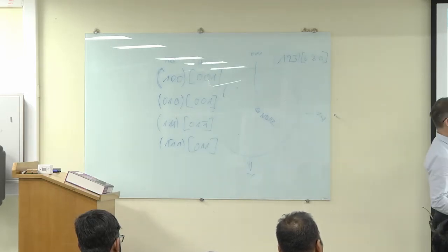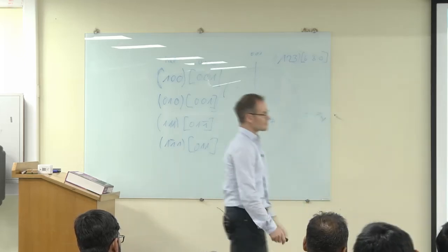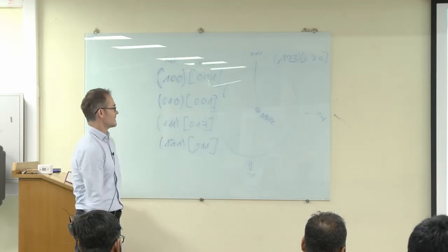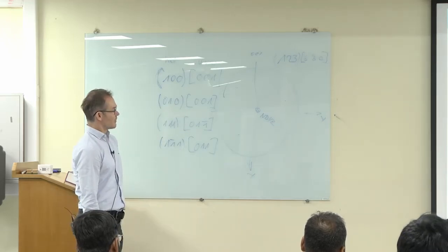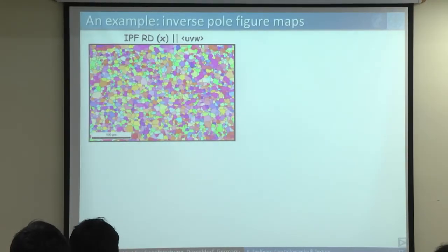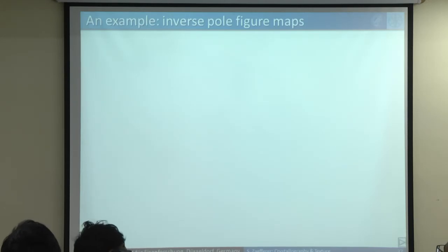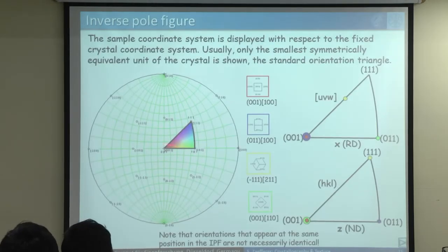And that means this crystal here, for example, if we would plot it now in the map, we would give it a red color. Yeah? Red for both, 001 is red and 100 is also red, and so on. And that's actually the inverse pole figure map, which we then see very frequently when we use EBSD. We are actually taking these colors out of the inverse pole figure, why is it not coming? Out of this overlay of color triangle.